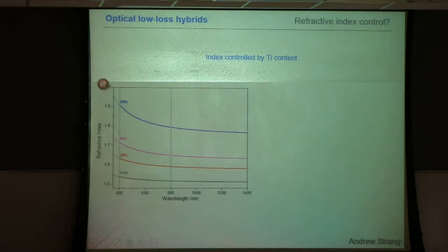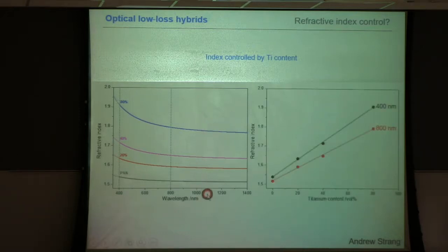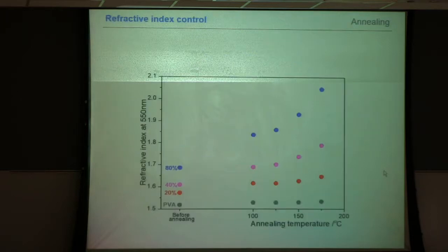Only at the very high content do we have somewhat of a dispersion, and the reason is really that the titanium species absorption at 300 comes in. As a material scientist, though, what is nice to see is a very nice linear dependency of refractive index with content. What does that mean? It doesn't matter if we deduce it at 400 or 800. This really shows us that the titanium species is very homogeneously distributed in our hybrid material. Otherwise, in case we would start to have aggregation or something, it would actually start to level off here. So this is an indirect proof of the quality of the dispersion of the titania.